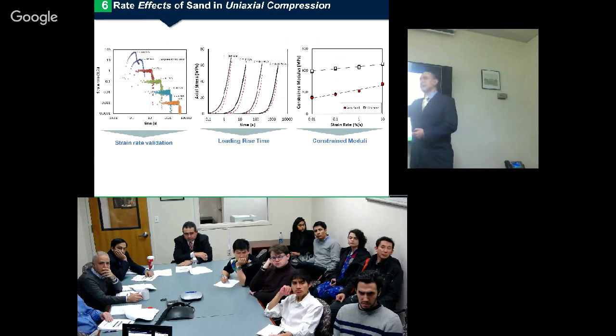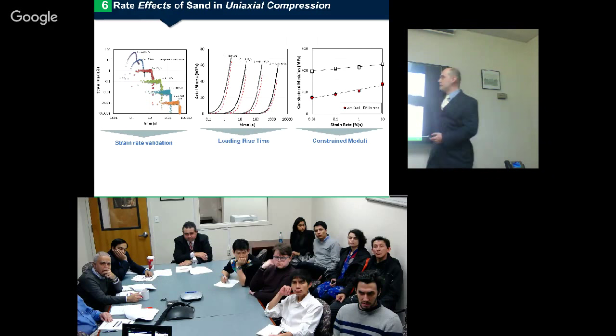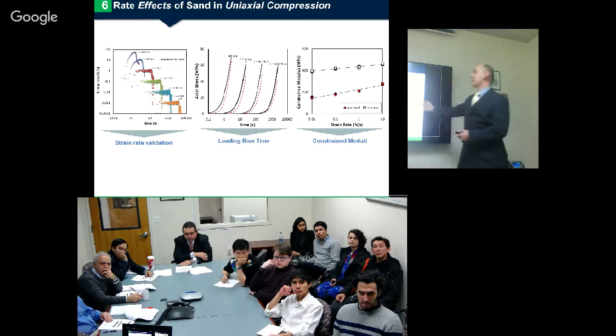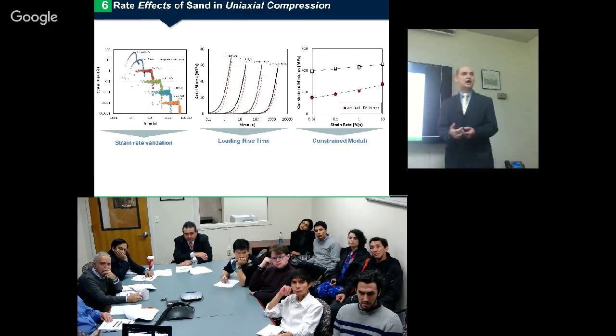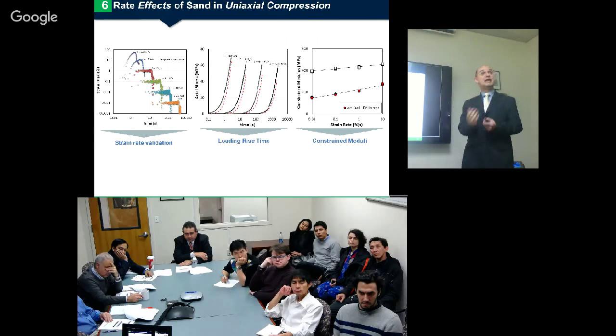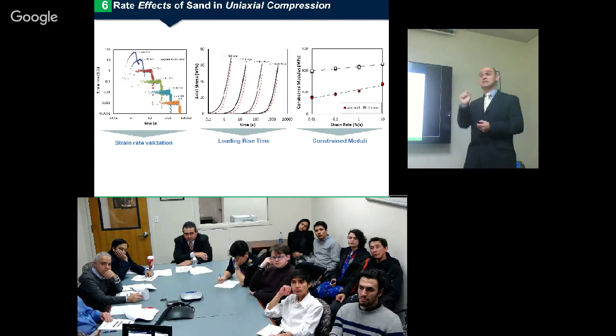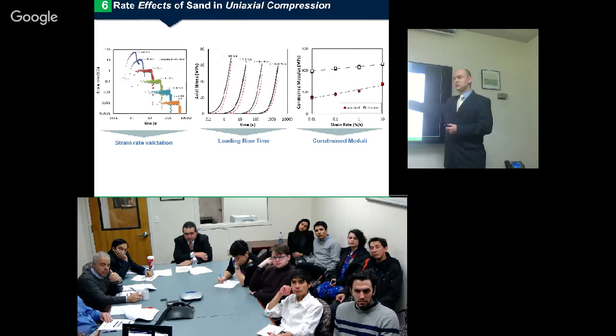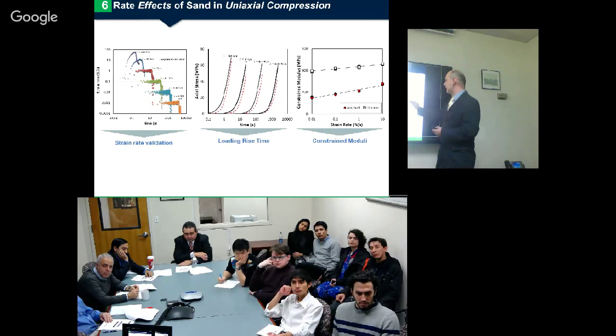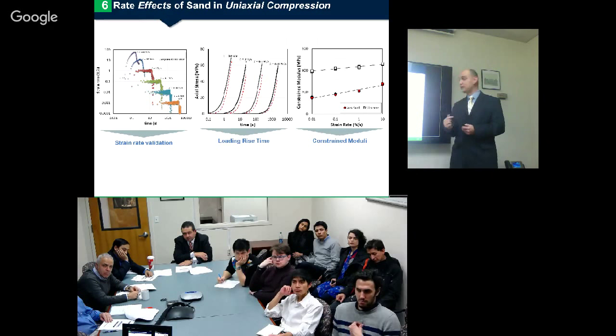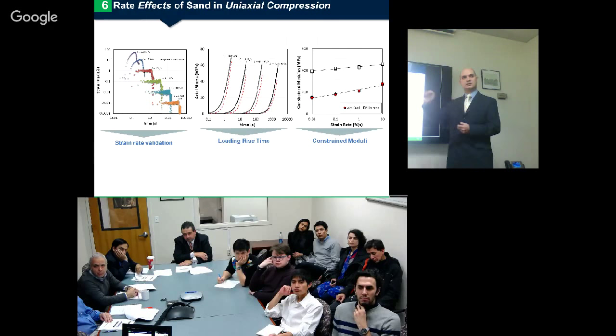This is a similar stress-strain curve that shows axial stress versus time in log horizontal scale to see the difference between silica and coral sand per each strain rate condition. And then after that, the constrained moduli that was taken from 5 to 10% axial stress per each condition gave rise to the initial conclusion that we can see some sort of an increase of the stiffness of the material as the strain rate is increased.